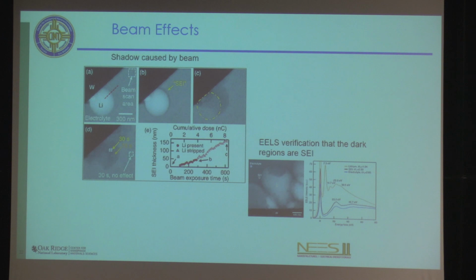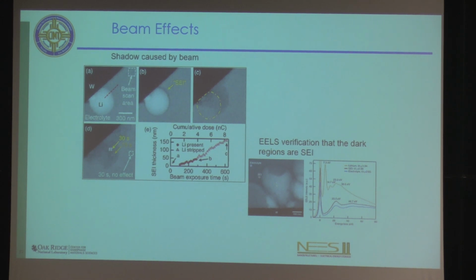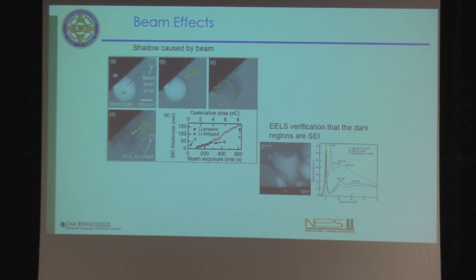And there was no real change in terms of looking at the surface, so there was no SEI that was deposited. But when they were depositing more lithium, and the beam was on, you start to form this SEI layer, or this thick SEI layer that's visible in the electron microscope.